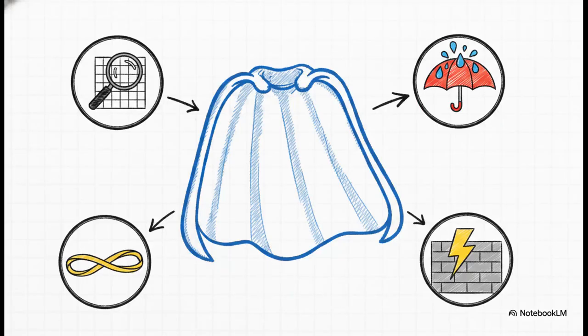And those physical properties are quite literally natural superpowers. Pure PDMS has a light transmittance of over 90%, meaning it's almost perfectly transparent. It has high hydrophobicity, basically it repels water beautifully with a contact angle up to 110 degrees. It's extremely flexible, completely biocompatible, and even acoustically tunable. But here's the catch. While pure PDMS is a fantastic water-repelling base, on its own, it's totally passive. It just acts as an insulator. So to become truly active, it needs an upgrade.